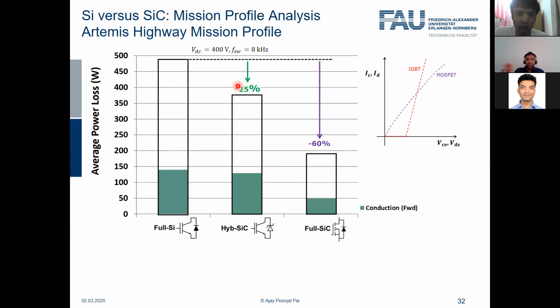But of course, this alone is not so impressive, or it does not tell us too much about the system, right? We would like to have some more details. And this is where the commutation-based method to split the power losses comes into play. We can now look at what the components are due to different root causes. For example, this green contribution is due to the conduction losses in the forward direction, so basically the active switch. And here, there is not so much difference between the first two. Why? Because the IGBTs are the same for both, so it is nearly the same. Maybe we see a small difference because of measurement tolerances in the characterization.